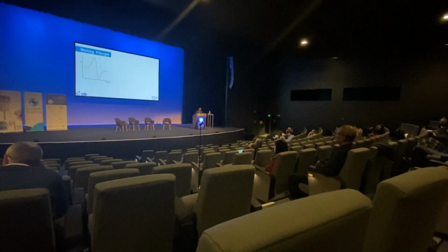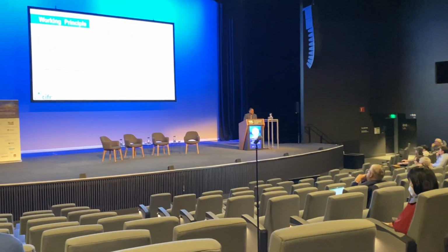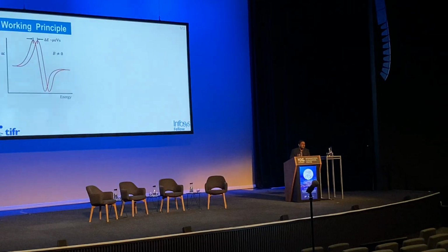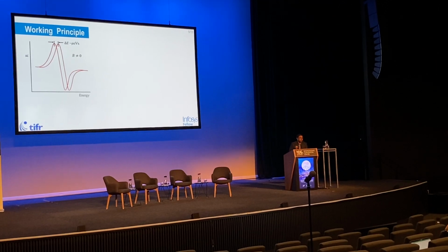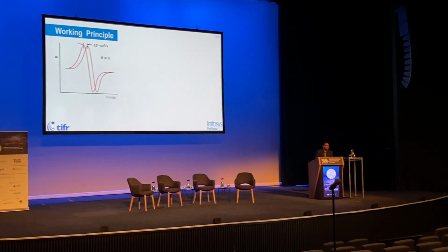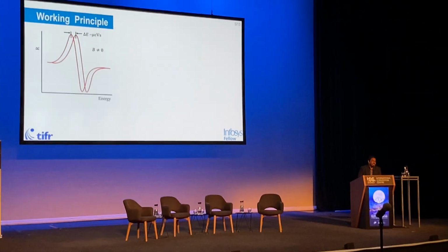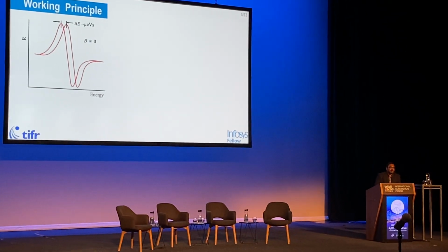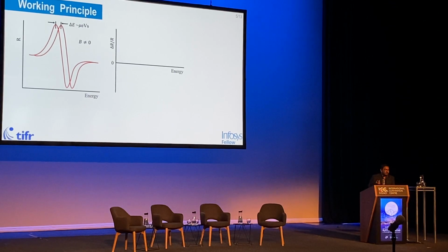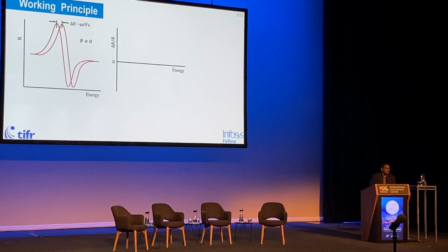So schematically, I just want to say how it is happening. So this is a standard reflectance spectrum for an exciton. And if we apply a magnetic field, there will be a shift in the transition energy, but the order of the shift, delta E, is on the order of micro electron volts, which we virtually cannot measure by subtracting two signals in a DC measurement. But there comes the importance of AC measurement, this delta R by R kind of measurement.